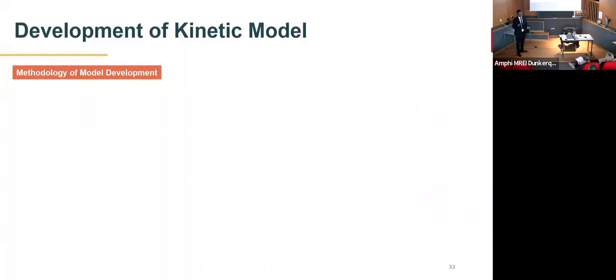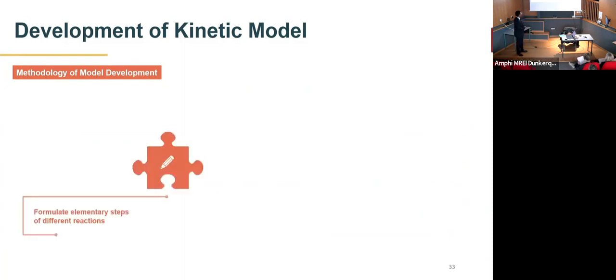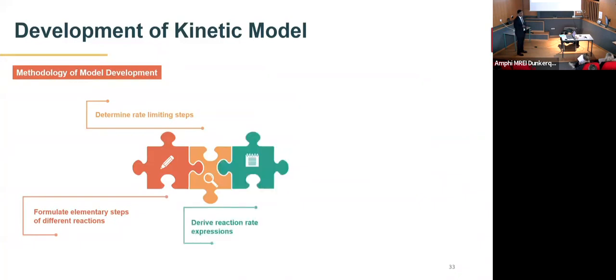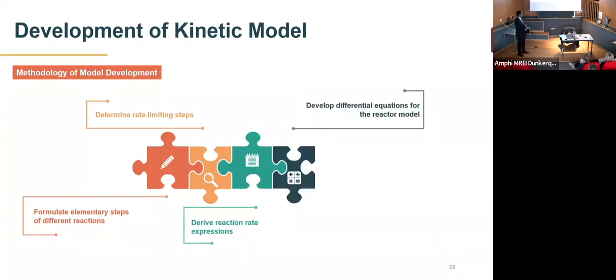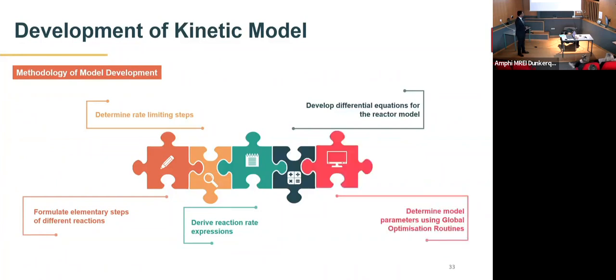So what was the methodology that I used for the development of the kinetic model for my reaction system? It was to first formulate the different elementary steps that are associated with the different reactions taking place in my system. Then determine the possible rate limiting steps for each of the reactions. Based on the rate limiting step, I derived the different reaction rate expressions. And I chose a reactor model in order to develop the differential equations that I would use for the optimization for the model parameter determination, and using an adequate global optimization routine in order to find the parameters.